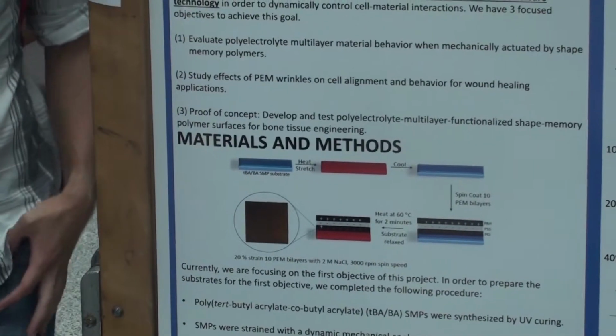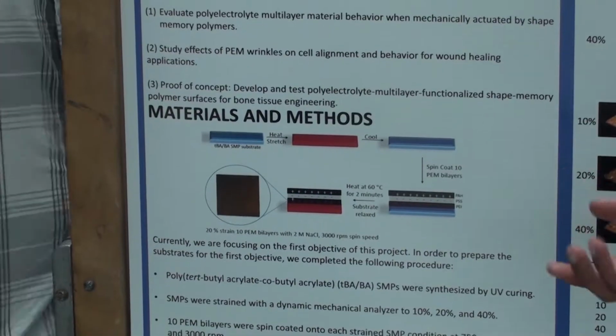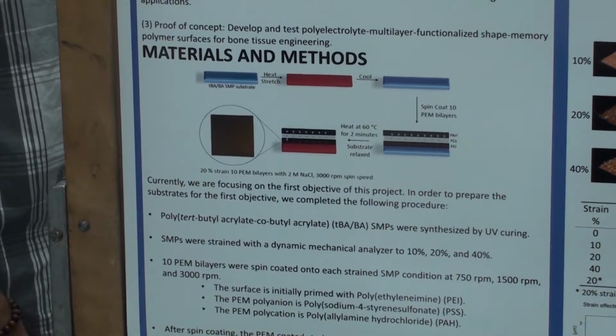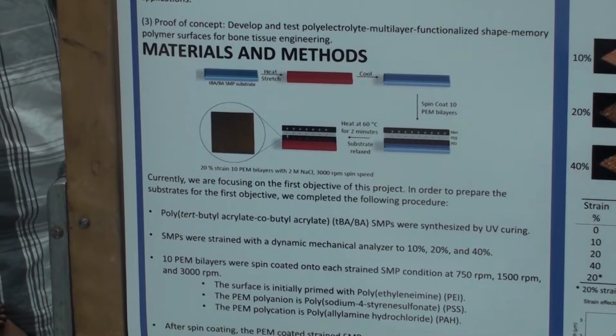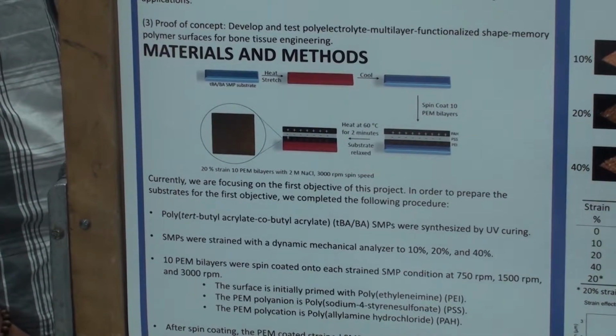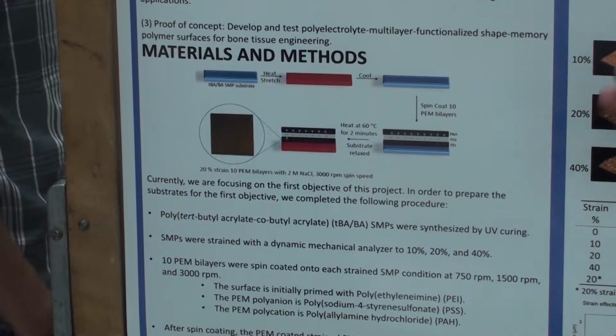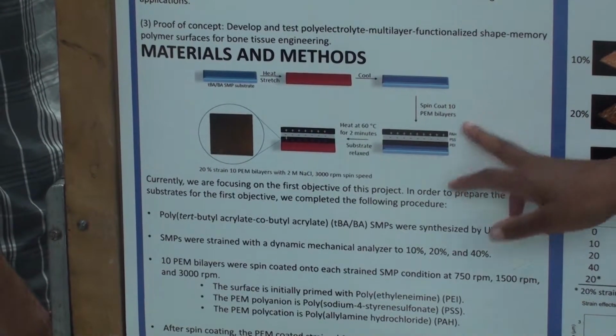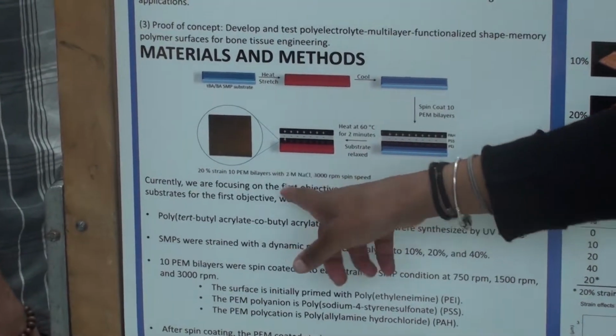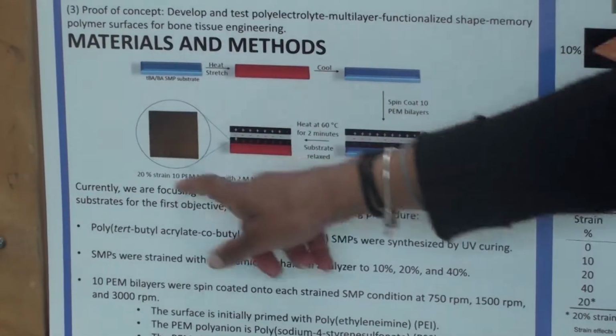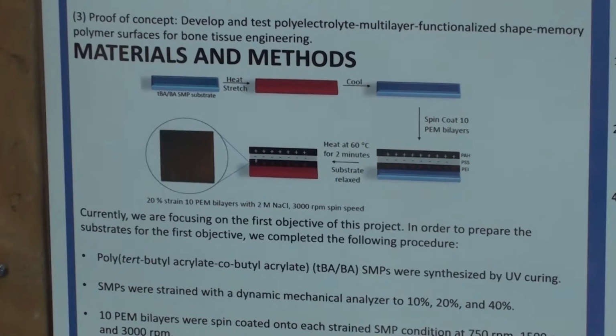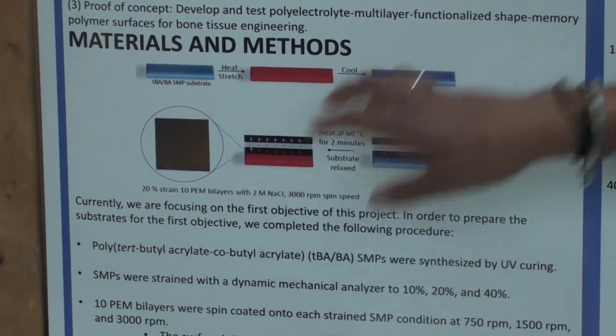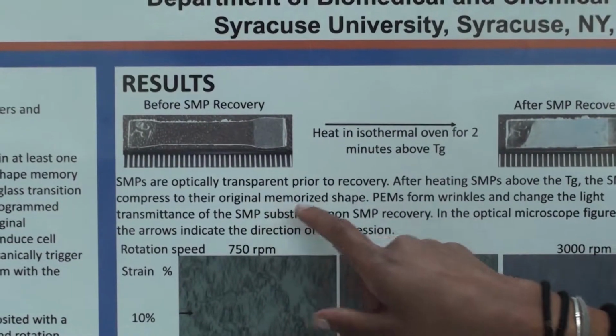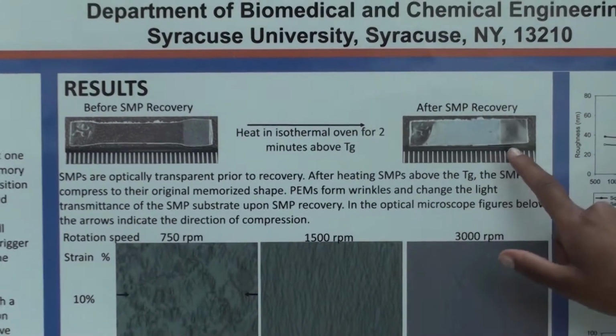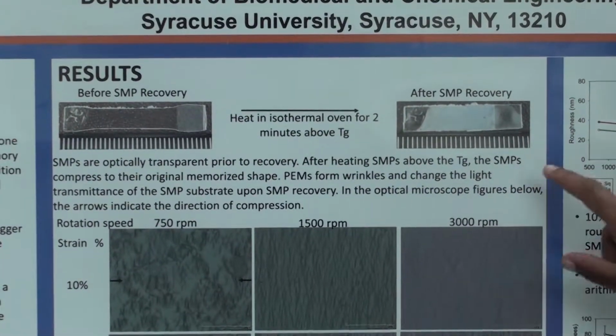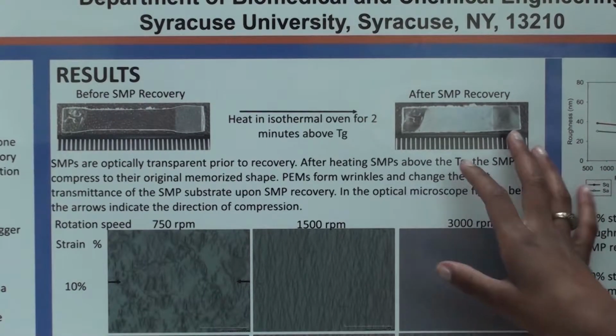And so what we do is we go through the basic steps of what I just showed with my hair to make the shape memory polymers at a new length, and then we coat it with polyelectrolyte multilayers. And so we can change the charge on top of our substrate to be either positive or negative. And then upon heating the substrate back up above its glass transition temperature, the polyelectrolyte multilayers compress and we get a wrinkle topography as shown here. Once that happens, there is an optical change in the polymer substrate, and this is how we initially know that we have wrinkles.